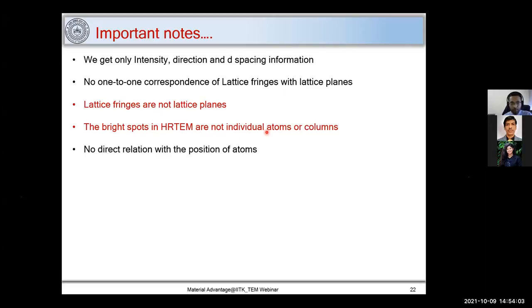Those are not even atomic columns. And there is no direct relation with the position of atoms. So this is very important. If someone claims that those are atoms, just walk away from that person. They can talk to a good microscopist. The important point I would like to make is that lattice fringes are not lattice planes, and whatever spots you see, those are not atoms.